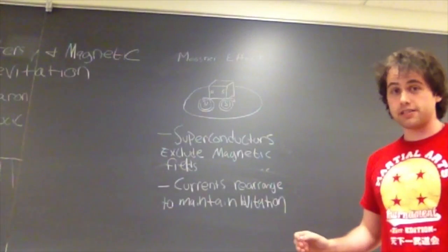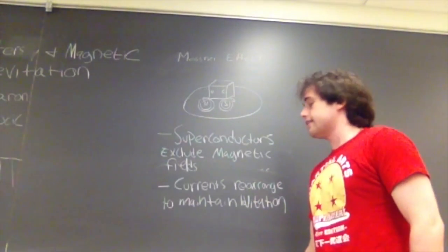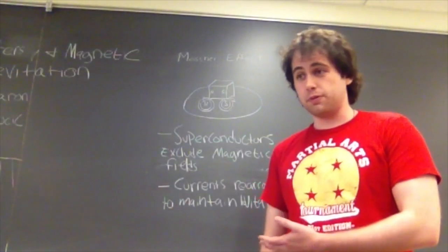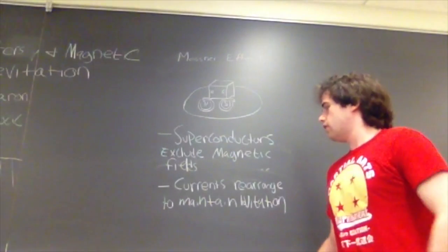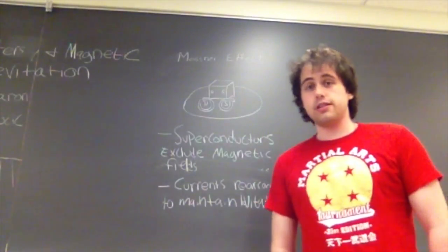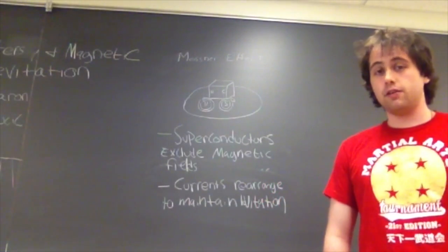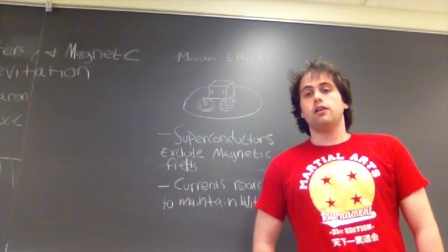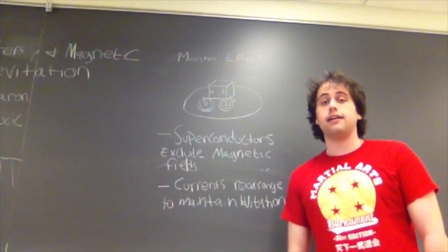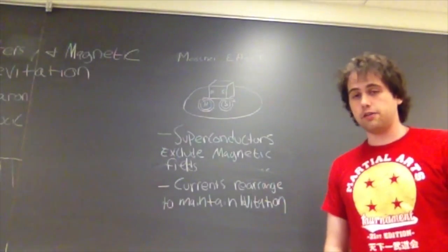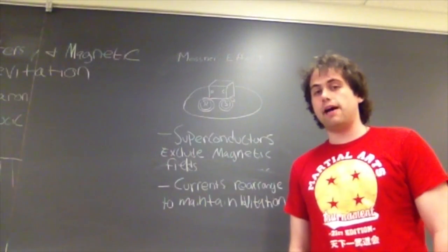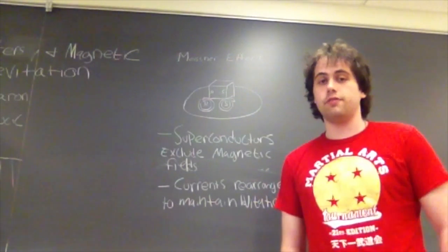And now a very interesting thing with the Meissner effect is that since the conductivity is so high in a superconductor due to the almost zero resistance, these north and south poles that are induced in the superconductor will rearrange themselves almost instantaneously. So as we spin or move this rare earth magnet on top of the superconductor, the north and south poles will rearrange themselves with it, thus keeping levitation no matter the oscillation or spin of this magnet.